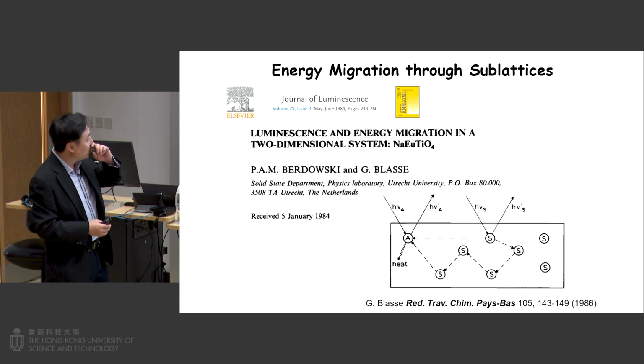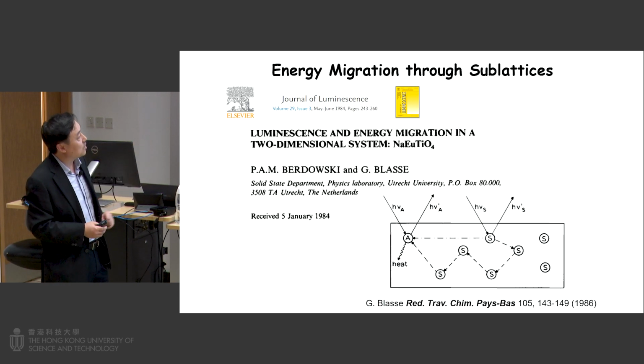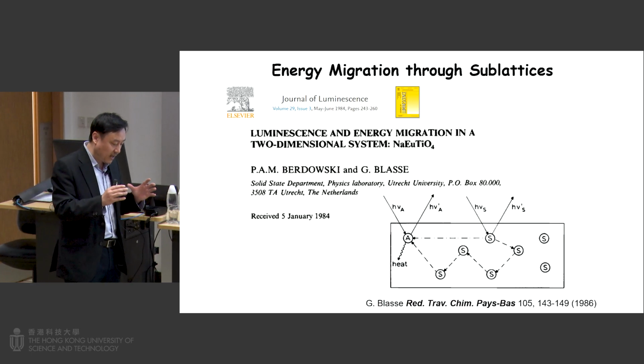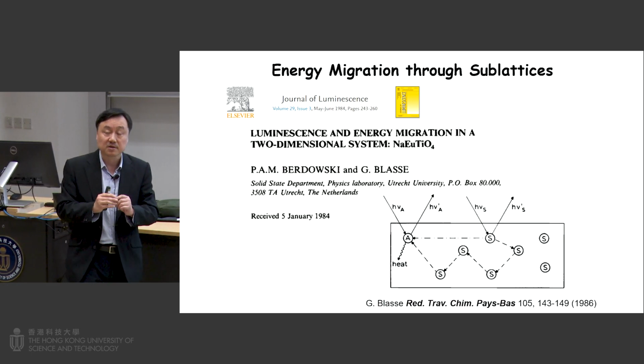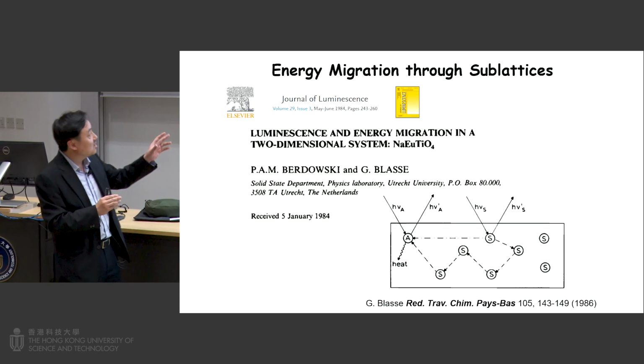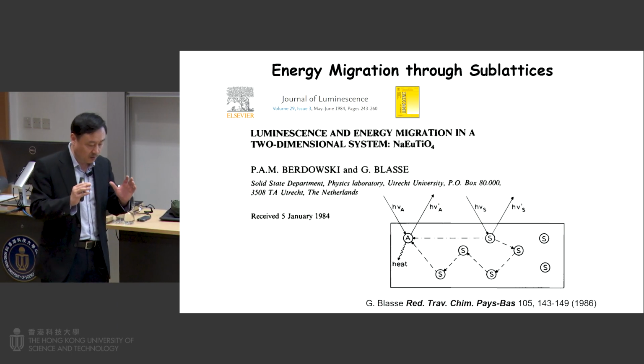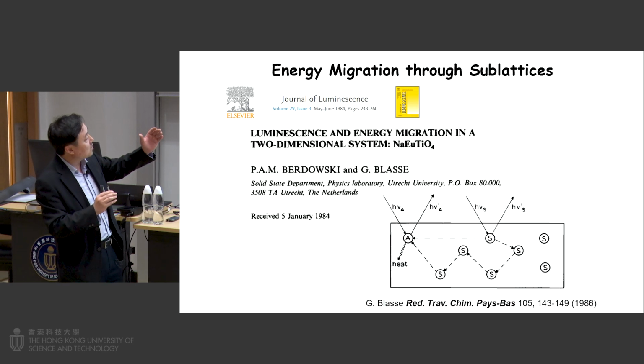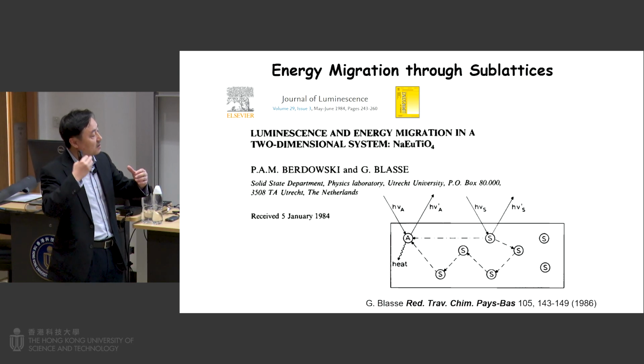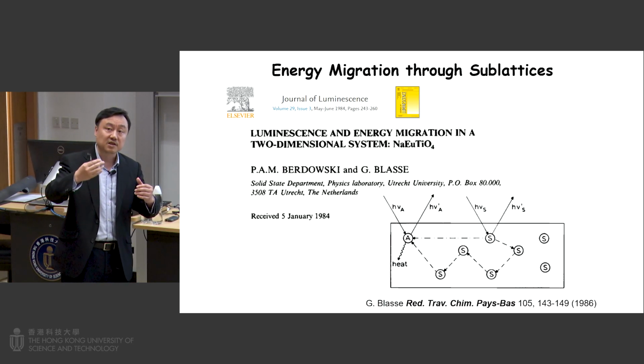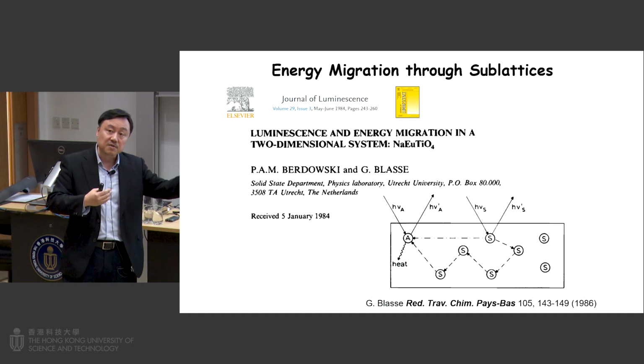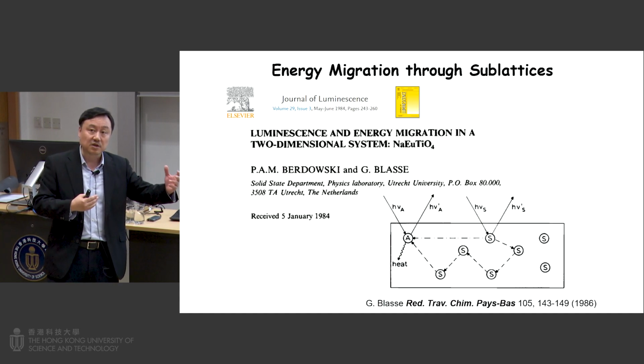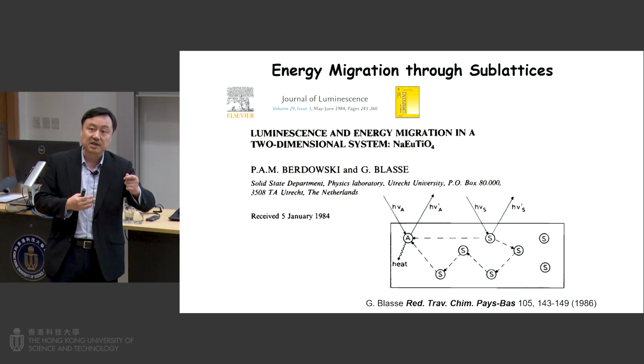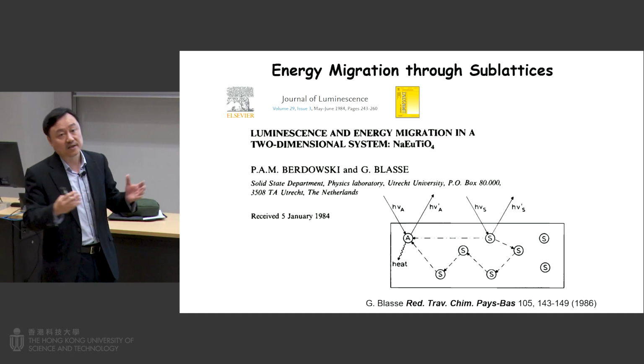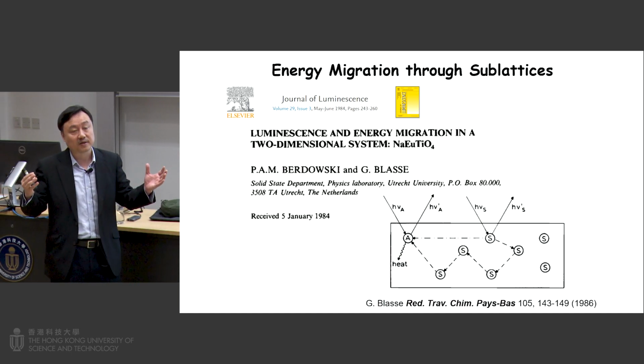I also want to highlight this energy migration. These lanthanide-doped particles have many interesting optical properties, and energy migration is one very interesting property. Energy migration means the energy absorbed by the lanthanide sensitizer can pass to the emitters over a long distance. This kind of long-range energy transfer can only be done using lanthanide ions. Quantum dots cannot do that. Organic dye molecules cannot do that.